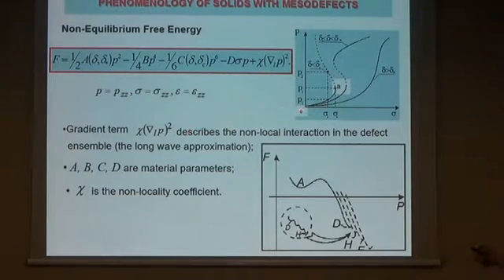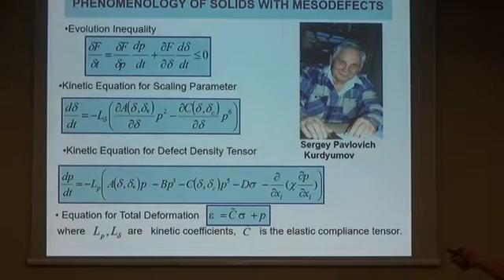It was very important that this statistical consideration allowed the formulation of free energy of solids with defects in terms of the above-mentioned variables and revealed characteristic nonlinearities that allowed us to predict specific free energy release. The subject of our interest is that there is a critical point where we have very specific nonlinearity, which includes a thermodynamic branch and a completely unstable branch, with this scenario of free energy decay.